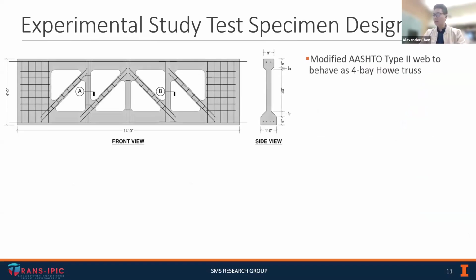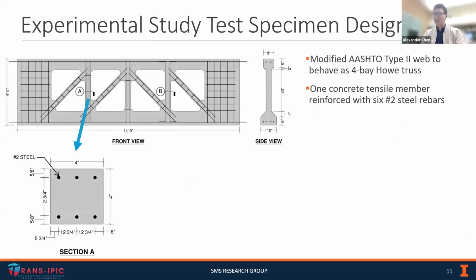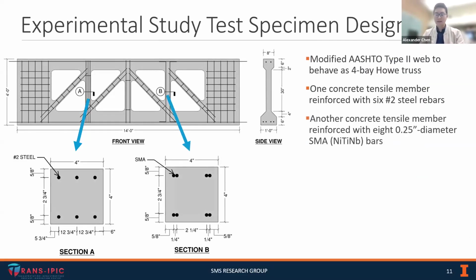To design the truss, we followed the same approach as mentioned before, where we take an AASHTO Type 2 and modify its web into a truss. We used the six 1/4-inch diameter steel bars in one of these tensile members, and for the other one, we used eight 1/4-inch diameter SMA bars. Now you'll notice that these 8 bars aren't distributed uniformly. Instead, we have them grouped into pairs in the corners of this member, and that was done so that when we heat these SMA bars to activate them and trigger the shape memory effect, we can heat pairs of SMA bars at the same time as opposed to one by one, which speeds up the process. I'll talk a bit more about the heating procedure in a later slide.